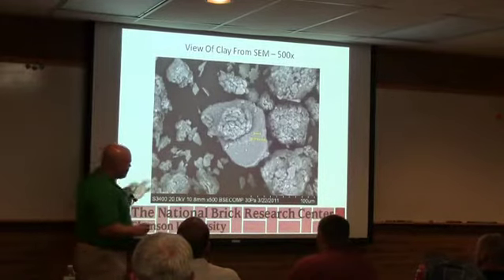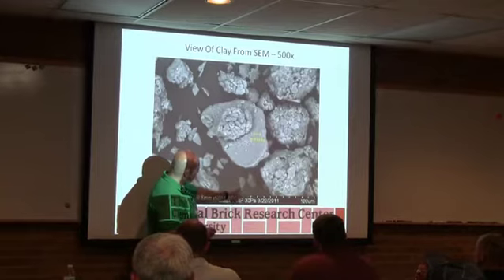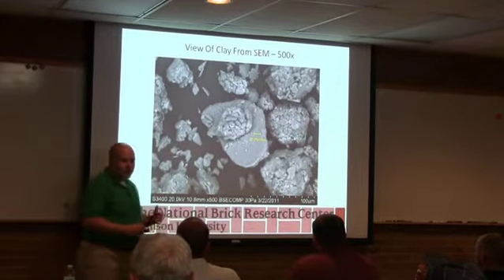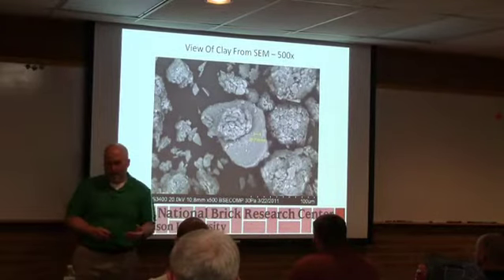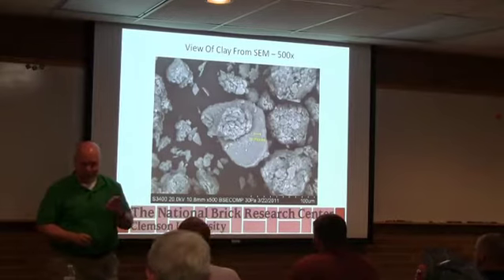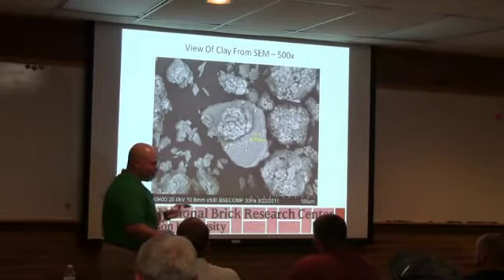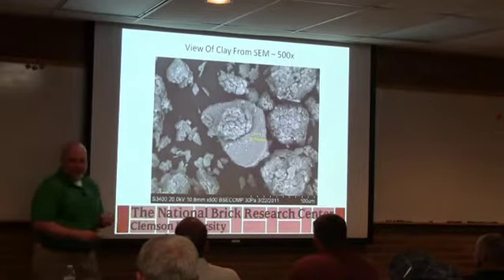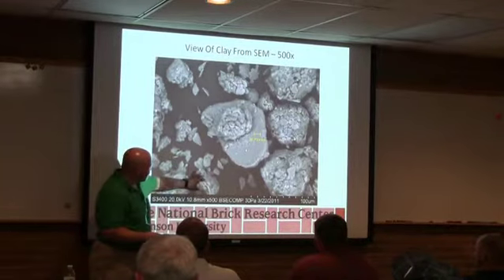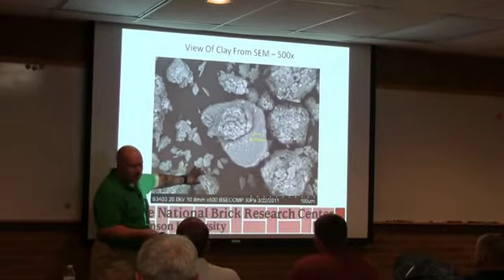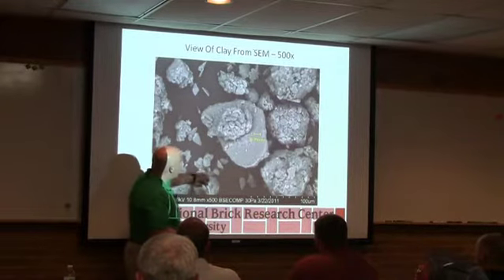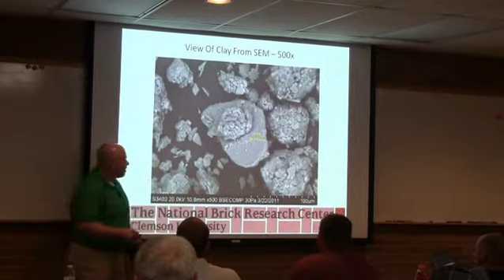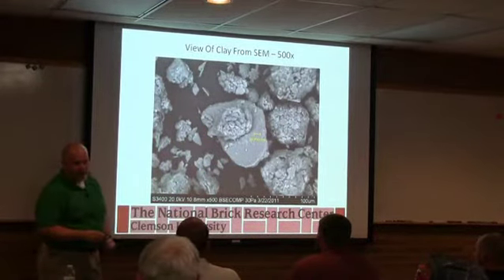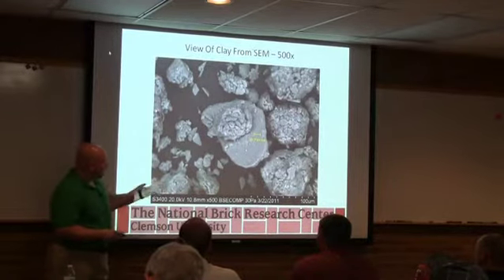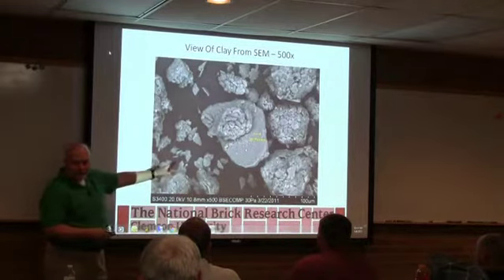And then this is another shot. The other thing to consider is these things are actually little plates. Okay? When you do a sedimentation analysis, for those of you who've done it, or particle size analysis, that's all based on the assumption that you're dealing with little spheres. Okay? So there is no such thing as a true particle size distribution. They all have assumptions. And we've got a technique now called laser scattering. So if you've done the sedimentation, you know it takes 2 days basically to get a result. It's kind of tedious. You don't get a lot of data points. The laser scattering can do the fine fraction in under 2 minutes. But they agree down almost to that point where you make the clay break, and then they diverge a little bit. And it's because of that assumption of particle size.